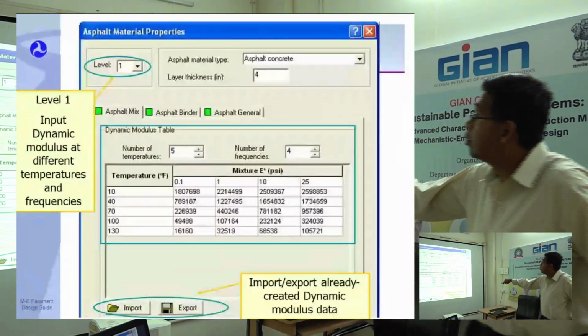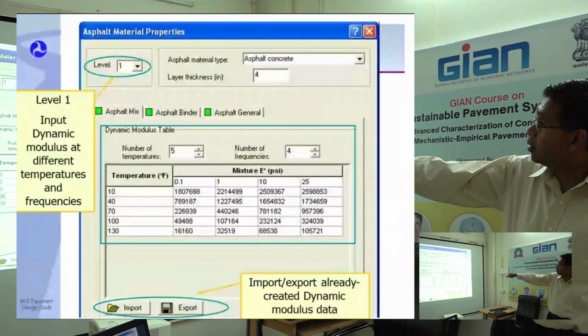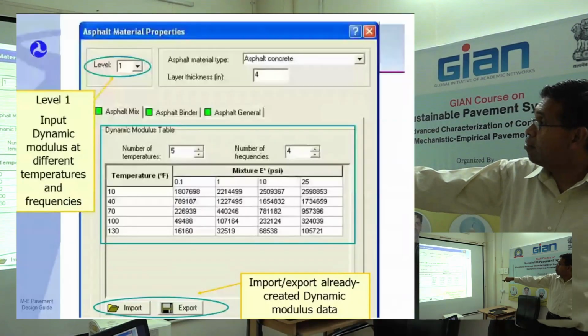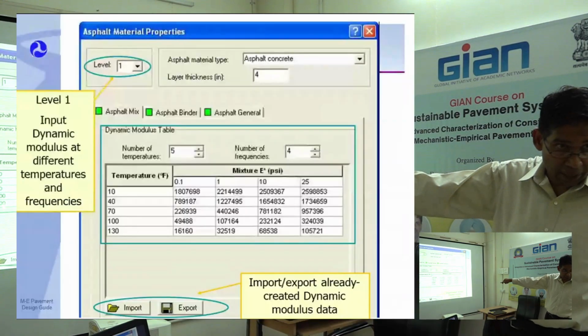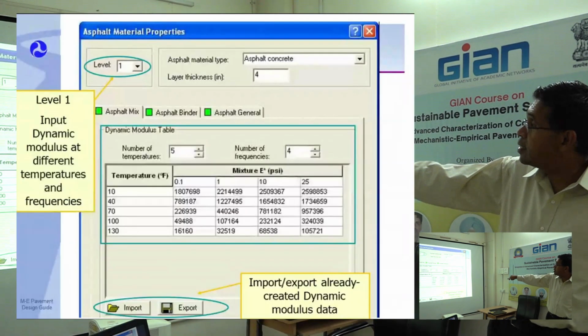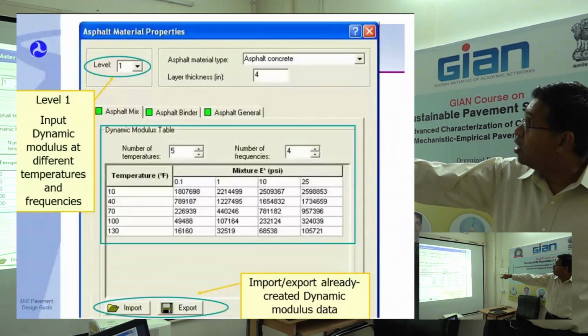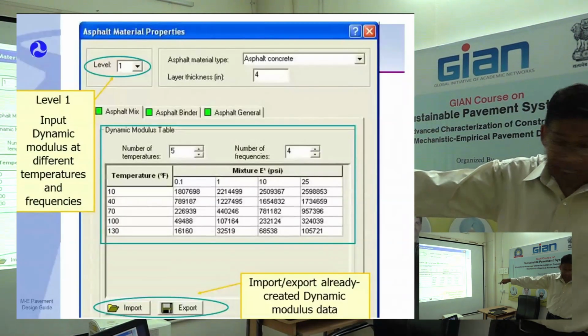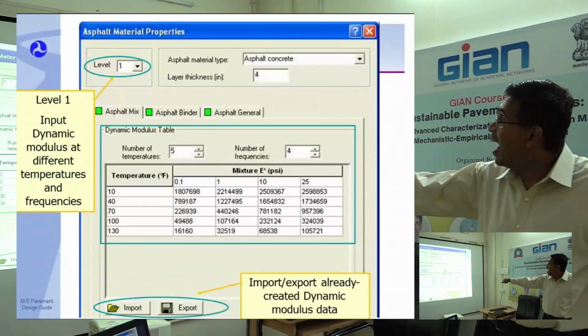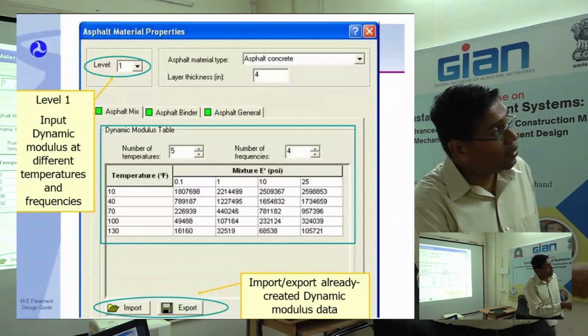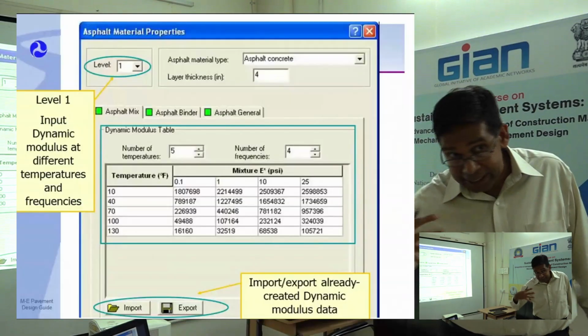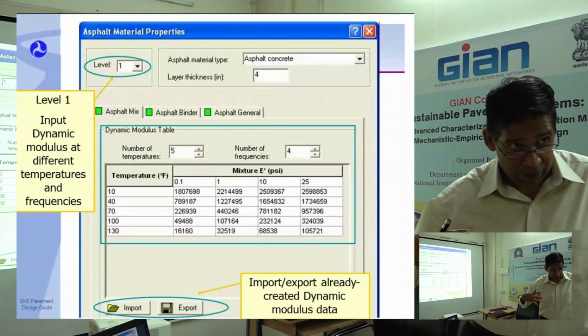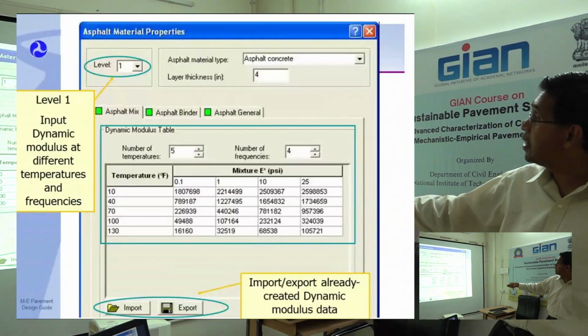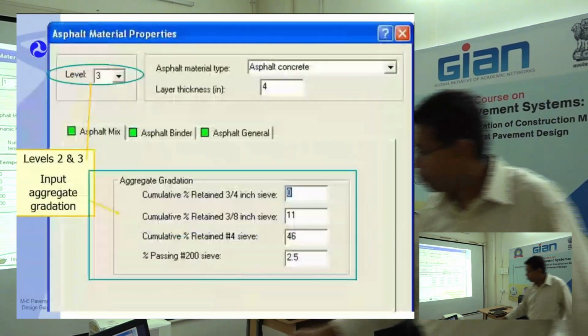This is the number, raw data. 5 temperatures, 4 frequencies: 10, 40, 70, 100, 130 Fahrenheit. Look at the numbers. This is what the input data is from the testing. That's all you have to give, and it automatically calculates the master curve. It automatically picks the right beta during the analysis. Does that make sense to you? Automatically. All you need is this right here.